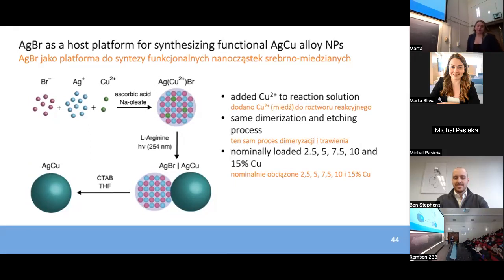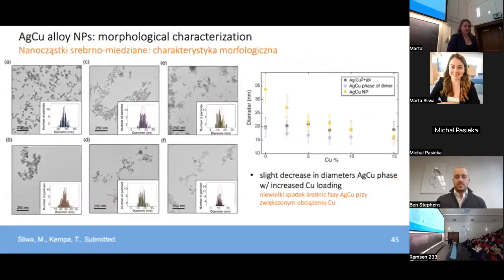Okay, so we're able to tune for the amount of copper that we incorporate into the system by simply adding different amounts of copper cations into the synthetic scheme or the process at the beginning of the reaction to achieve nominal loadings of 0 to 15% copper. And nominal here, again, is also a keyword that we will revisit a little bit later.